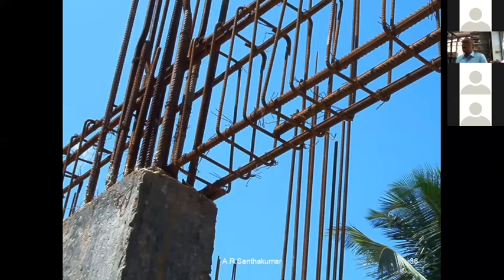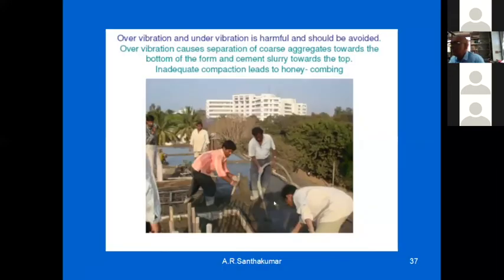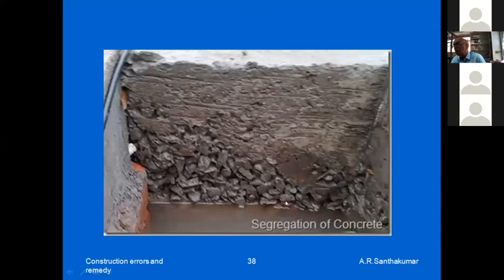This is another place, a multi-story building where we had witnessed vibration was done not in a scientific manner, expecting good amount of consolidation of concrete. Instead, over vibration was done, and because of the over vibration, all larger particles had settled down at the bottom, and only 6 mm down particles have settled at the top, indicating that several beams are suffering from the problem of segregation. With the result, when we checked the core strength in the top reaches of the beam, where maximum compression comes in the beam, it was only around 10 to 15 MPa. And this is one of the reasons why plastic hinges could easily form, with the compression failing and tension bars pulling out.